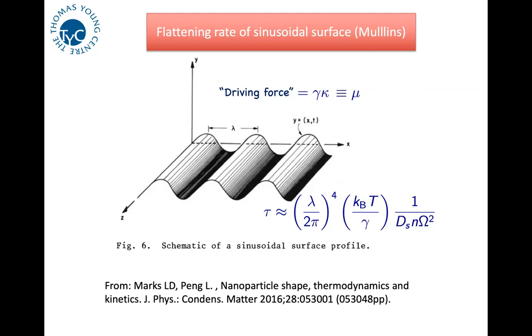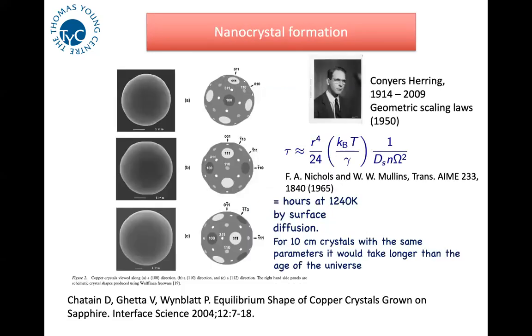If it's not interrupted by faceting, of course, as long as you have a surface that will do that. And to do it on real crystals is much more difficult because the time scale is so slow. As I said in my previous slide, it might take 1,000 years to generate an equilibrium shape of a crystal a few centimeters in size. And that's at least partly because of that length scaling as a power of 4.